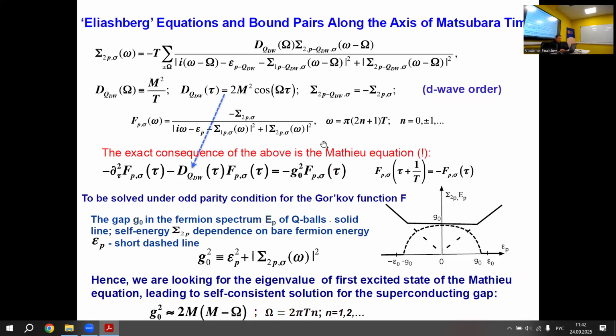the following. This is actually the square of the superconducting gap. What is G sub 0 squared? This is the sum of the bare electron dispersion function, electron energy, with respect to chemical potential, and this is self-energy sigma 2 modulus squared. The sigma 1 was also calculated, but it just renormalizes slightly the Fermi velocity and shifts the chemical potential, so we throw it away. And then if you assume that G sub 0 squared is related to sigma 2 in this way, you get exactly this Mathieu equation. It's Mathieu equation because this so-called potential is actually cosine omega tau.